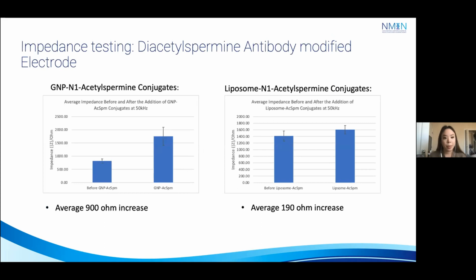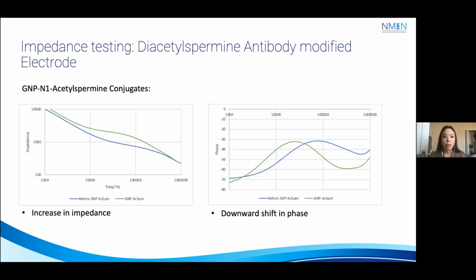And based on impedance testing with gold nanoparticle conjugated to diacetylspermine conjugates, we were able to observe a 900 ohm increase. And then with the liposome diacetylspermine conjugates, we were able to observe an average of 190 ohm increase. And then based on the impedance and phase readings from a single electrode, incubated with the gold nanoparticle diacetylspermine conjugates, we were able to see this characteristic increase in impedance after the addition of the gold nanoparticle and a downward shift in phase.